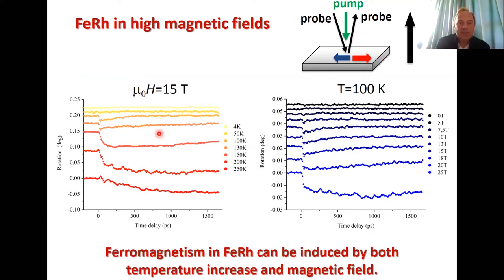What we see here is that it doesn't matter whether you increase temperature at fixed field, or you increase magnetic field at fixed temperature, you can trigger the phase transition in both cases. A magnetic field with a strength of about 25 tesla is already strong enough to launch the phase transition. So ferromagnetism in iron rhodium can be induced by both temperature increase and magnetic field.